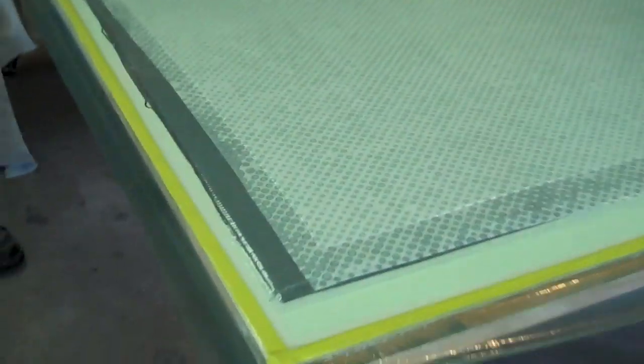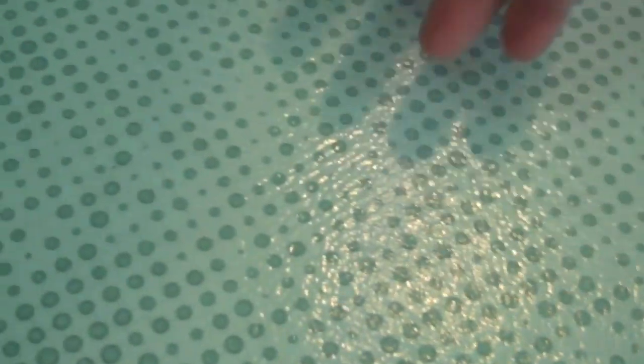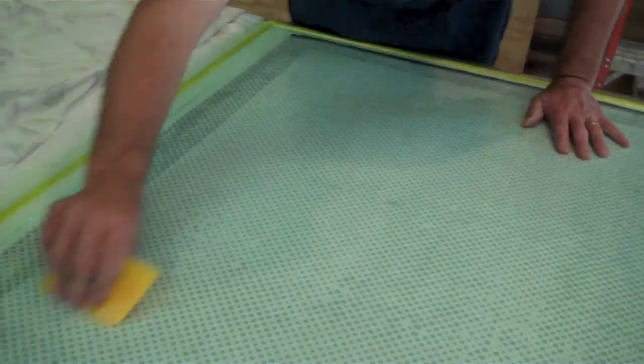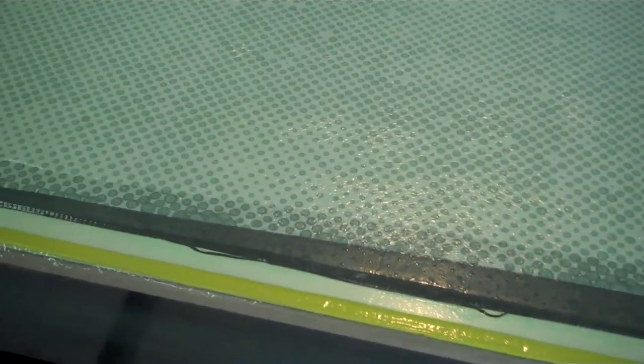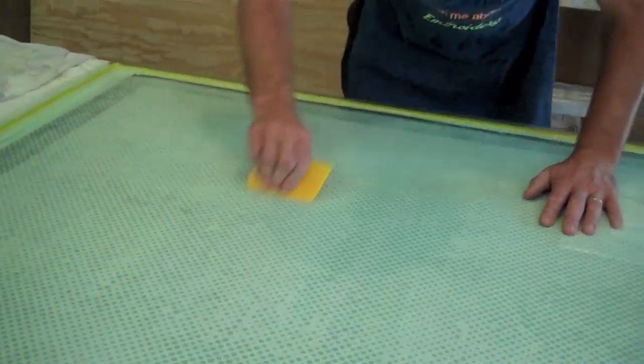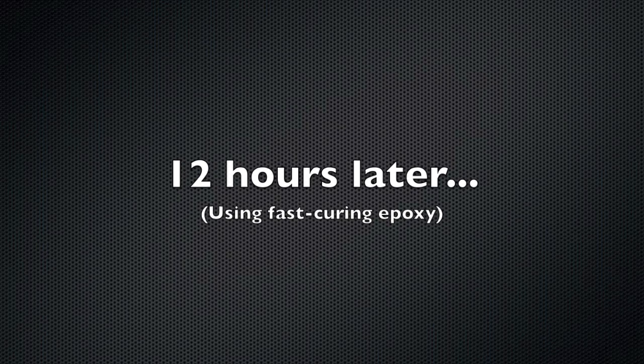Oh yeah, you can see it pulling nicely through. It's nice and even. If it's too wet it'll just go like blue green. Or if it's not enough, it'll be really white. But it's just coming out nice. Nice and even through those. This is probably the greatest thing you've seen today.